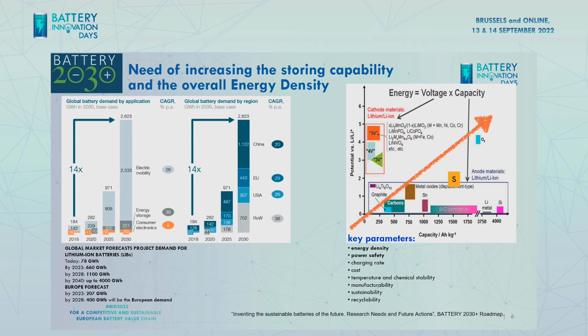And on the other side, the anode is working on the capacity. This is the reason for the movement, and the need, to go again to metallic lithium, whose capacity is much higher. But in the middle, you also have two different systems, such as sulfur and oxygen. Sulfur has, for sure, lower voltage, but much, much higher capacity than many other cathodes. So combining sulfur with lithium can be a good solution to strongly increase the overall energy density.